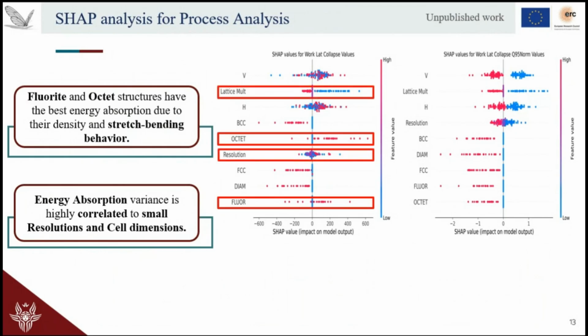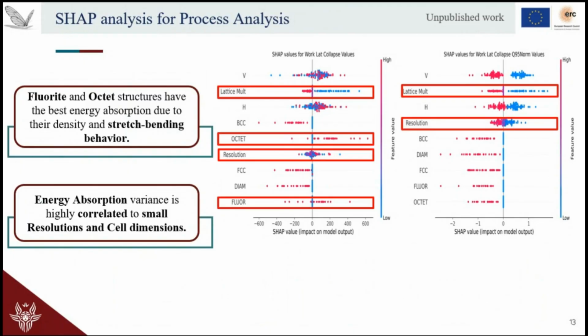But we have also some influence of the cell scale of the lattice. So when the cell is smaller, it seems to increase the energy absorption. But looking at the scatter of the distribution, we see that it's increasing for small values of cell size and for small values of resolution. And that's an indicator of the defect-inducing parameters. So those two, even if they are increasing the energy, they are increasing also the defects inside the specimen.